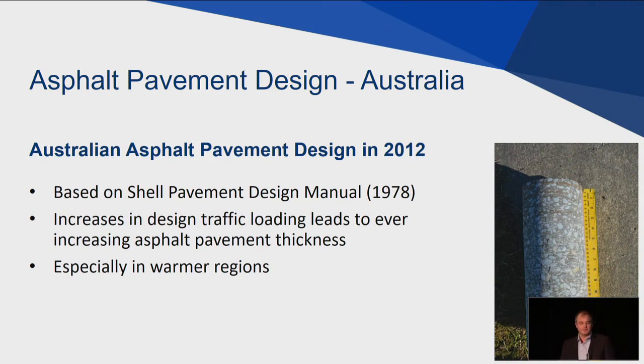So back in 2012, and actually still to this date, the Australian Asphalt Pavement Design method was mainly based on the Shell Pavement Design Manual of 1978 that some of you may be familiar with. And what we were seeing in 2012 was that the ever-increasing design traffic loading led to ever-increasing asphalt pavement thicknesses. Just to give you an idea, in the great state of Queensland, where I live, they were seeing designs of 400 millimeters of asphalt, so that's 16 inches, up to 600 millimeters of asphalt, so that's 2 feet of asphalt.